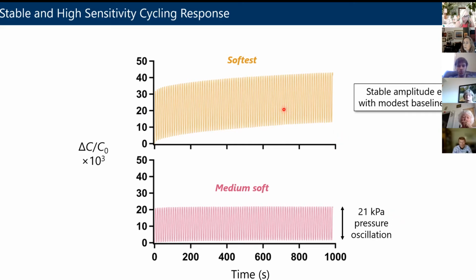And these are 2 different materials that we've made, 2 different bottlebrush elastomers. One of them's kind of medium soft, and one of them's even softer than that. And you can see you get a bigger signal out the softer the material is. The amplitude of the oscillation is much larger. You get a little bit of baseline drift, but even when you do, you have a stable amplitude, up and down, up and down.